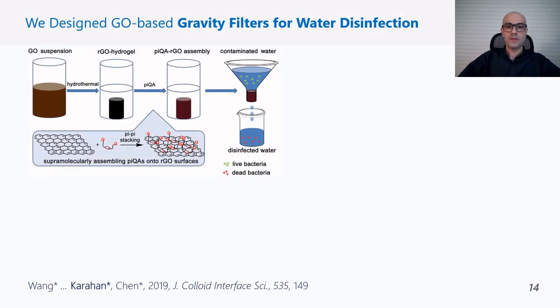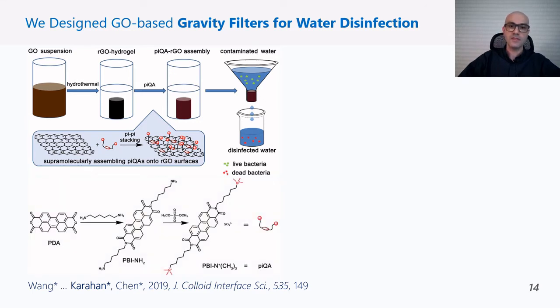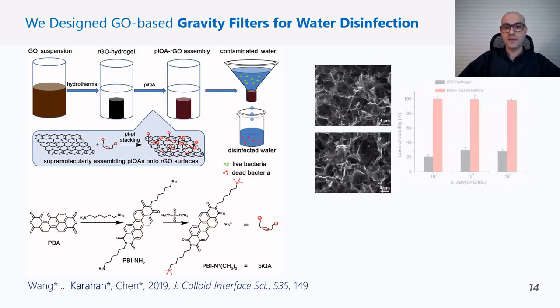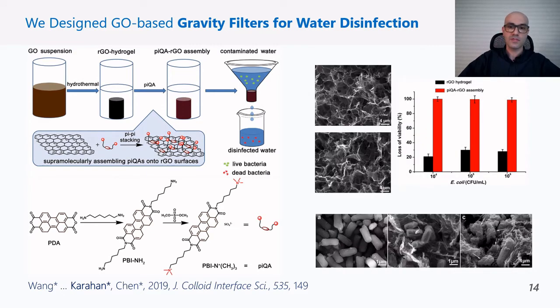In addition to biomedical applications, the antimicrobial activity of graphene materials and their composites is also interesting for environmental applications. In a recent study, for example, we demonstrated that graphene oxide-based sponges can function as a point-of-use filter. And when it is functionalized with a specially designed quaternary ammonium compound, the resulting assemblies showed very promising antibacterial activity against gram-negative pathogens.